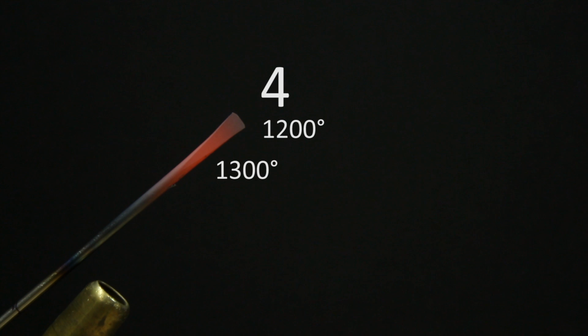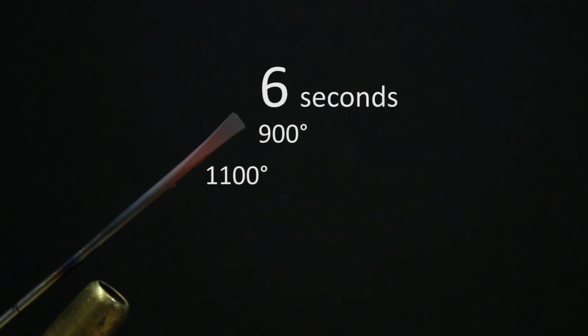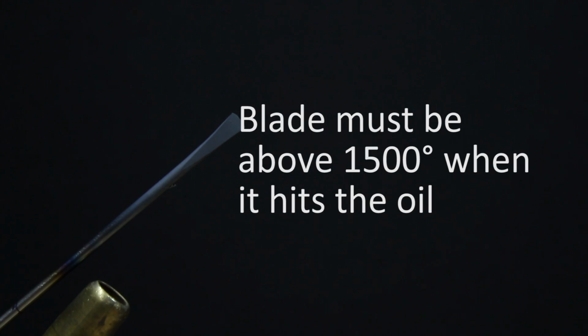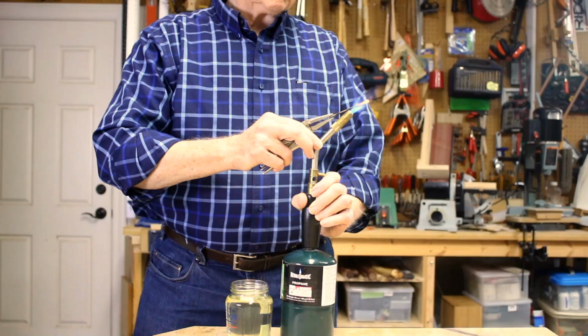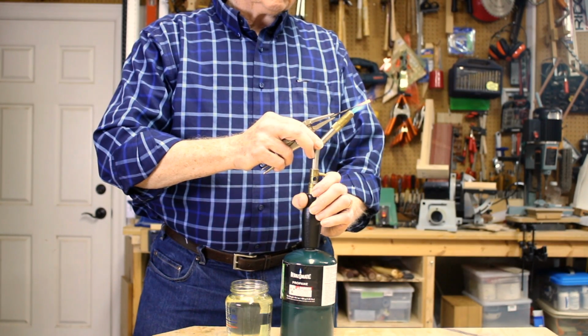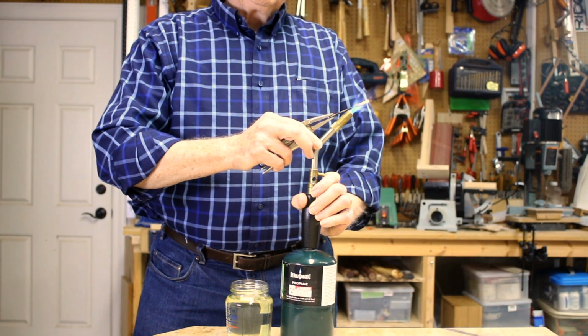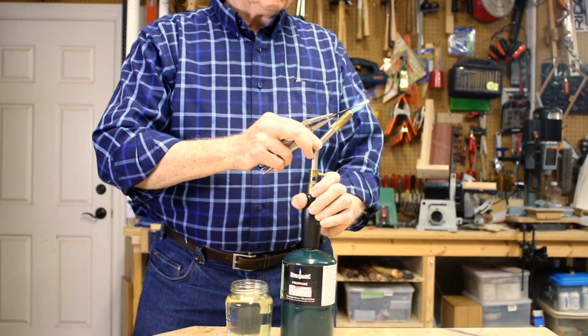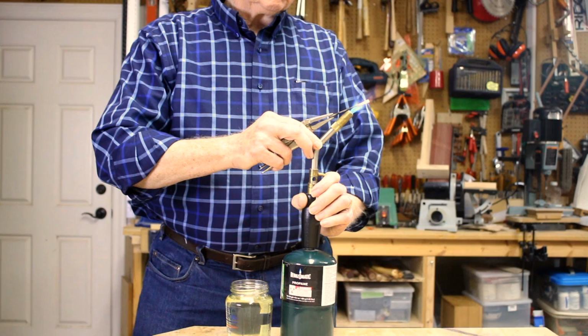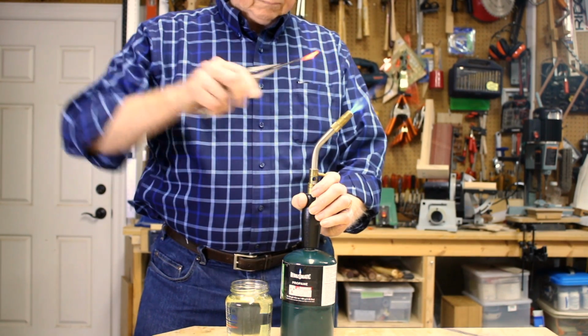As you can see, this thin blade loses over 100 degrees of temperature every second after it leaves the flame. For the oil quench to work correctly, steel needs to be above 1500 degrees when it hits the oil. Our strategy is to heat it up to about 1700 degrees and then work rapidly to get it into the oil as quickly as possible after moving it out of the flame before it cools to 1500 degrees. You have about 1.5 seconds.